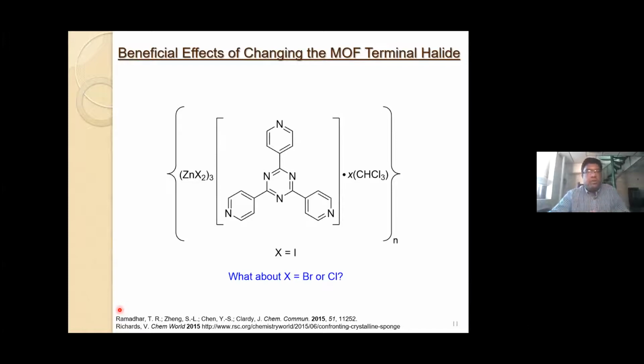Another thing that we wanted to focus on was what would happen if we changed the MOF terminal halide ligand from iodine to bromine or chlorine. We wanted to do that because X-rays interact with electrons, and there are a lot of electrons in iodine. That would cause the host to contribute greatly to the overall X-ray signal, which we call the structure factors, which could potentially drown out the signals from the guest. So we thought, well, what if we reduce the electron count, changing iodine to bromine or chlorine? Then you reduce the electron count of the host and potentially reduce its contributions to the X-ray signals, and that allows you to potentially see the guests better